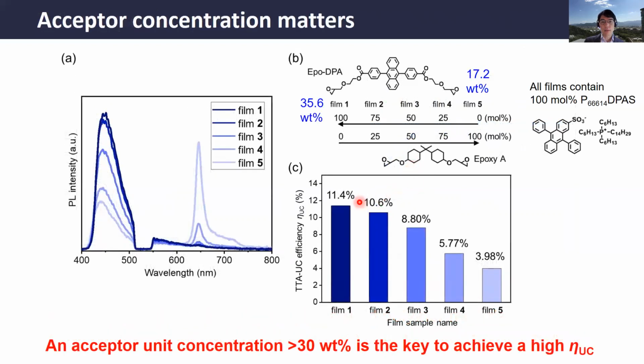To understand such a high efficiency, we systematically changed the acceptor concentration. We kept the concentration of the ionic liquid acceptor, and changed the concentration of the acceptor in the epoxy network. By changing the ratio between the epoxy with and without the acceptor unit, we could tune the acceptor concentration from 35 weight% to 17 weight%. We observe a high upconversion efficiency over 10% when the acceptor concentration is above 30 weight%. When we reduce the acceptor concentration, we observe a decrease of upconversion efficiency to 4%.